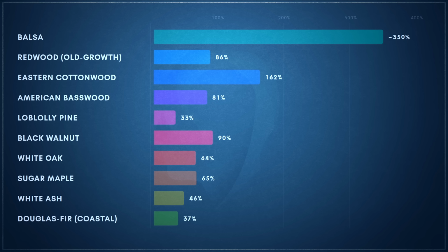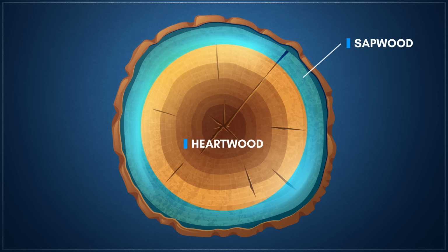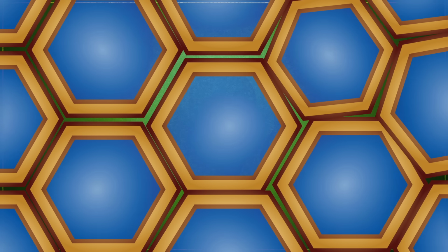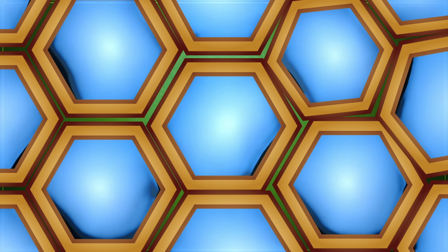This variability exists not only between different species, but also within individual trees. In living softwoods, the moisture content of the outer sapwood is usually significantly greater than that of the inner heartwood, whereas in hardwoods, this moisture differential depends heavily on the specific species. As green timber is dried, the free water located in the cell cavities separates first, evaporating at a relatively fast rate.